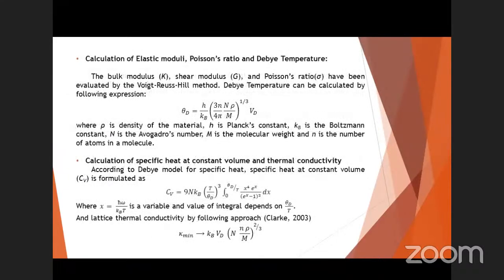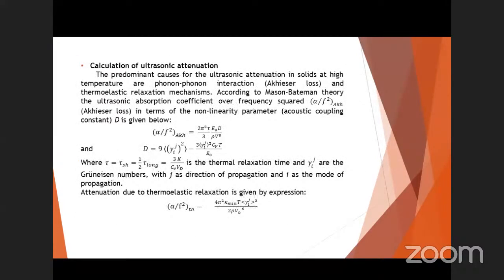Now after finding the Debye velocity, we found the Debye temperature and then Cv. These are the formulas for attenuation. Here E0 is the thermal energy density, and tau is the thermal relaxation time. Gamma is the Grüneisen number, which is calculated in 41 different directions, and then averaged and squared for use in the formulas.